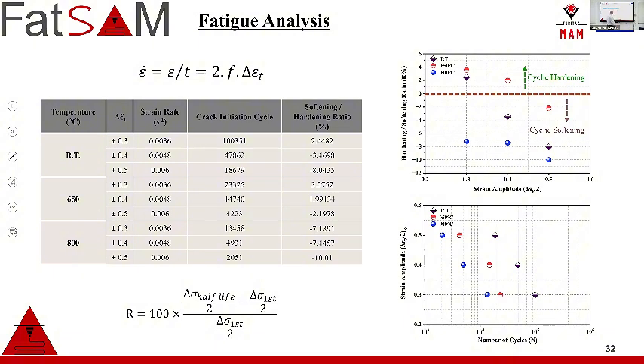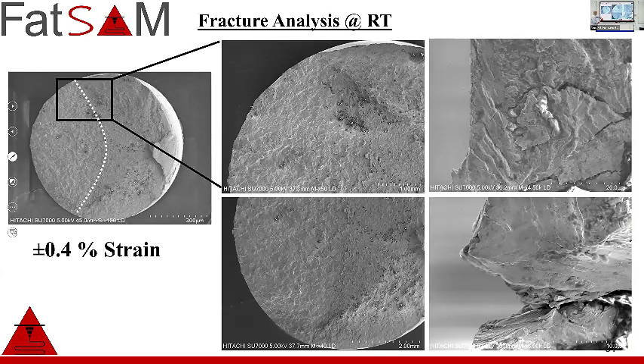When we look at the number of cycles and strain amplitude, we will improve this graph. Two things are important. In strain control low cycle fatigue tests, you don't necessarily need to obtain an SN curve. In general, we use SN curves, isn't it? But here, you can obtain an EN curve, which is, I believe, much more useful if you are doing some ANSYS design for a part-specific application or something like that. That's the biggest advantage. I can go to the fracture analysis and complete it because we are almost done.